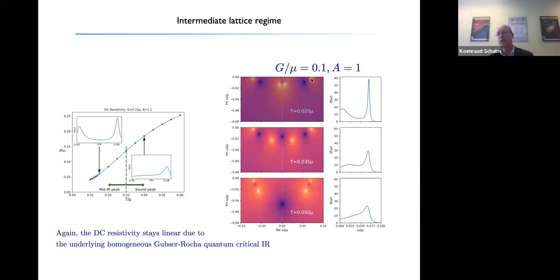So even though I'm here no longer at weak lattice potential strength, in a formal sense, Umklapp hydrodynamics is no longer valid. You still very clearly see the 4 peaks that you would also derive from an Umklapp hydrodynamics analysis, which would be perturbative in A. And if you look at the optical conductivity, you see indeed beautifully both these peaks. Here, this is this mid-IR peak, the one that we made such a deal about, the one that you also see in experimental strange metals. And here is this other peak. This is the Umklapp sound mode in the system.